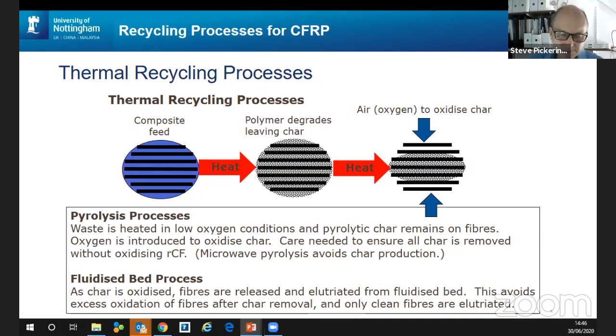And so to recover good clean fibers, you'd need to apply some air to give some oxygen to oxidize the char. And in a pure pyrolysis process, where you might have a stationary bed, the air comes in from the outside, initially oxidizing the char on the outside of the fragments. But to clean the fiber, to remove the char in the middle, you've got to allow enough time for that to take place, and you don't want to overcook the fibers on the outside in a process like that.